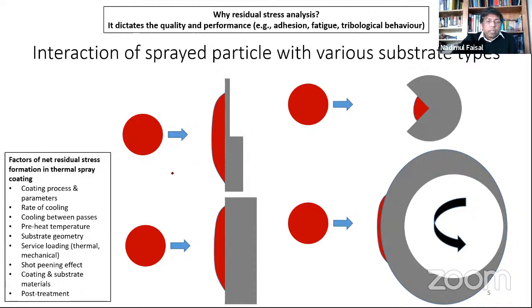So there are a number of factors which can lead to net residual stress. These can be different thermal spray techniques, the process parameters involved, as well as the temperature and rate of cooling between passes. If you're doing preheating or heating during, or post-treatment heat treatment can be done. Service loading, shot peening, as well as the coating material and substrate materials. All these will have an impact on the final coating manufactured.